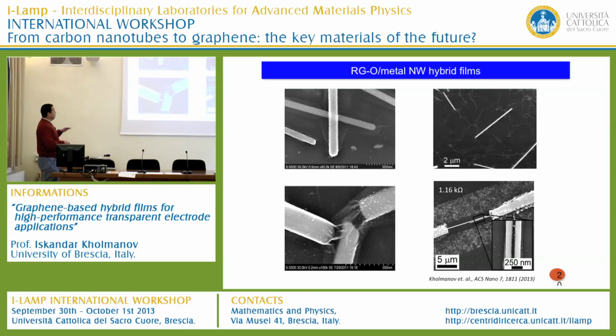Another feature is when you deposit the nanowire film, you can see many nanowires that are located very close to each other, but they are not contacted. Even a very small gap between them gives no electrical conductivity. So when you cover this kind of structure with reduced graphene oxide, you can provide a two-dimensional conductive channel that can facilitate the transfer of charge carriers through the nanowires and RGO.